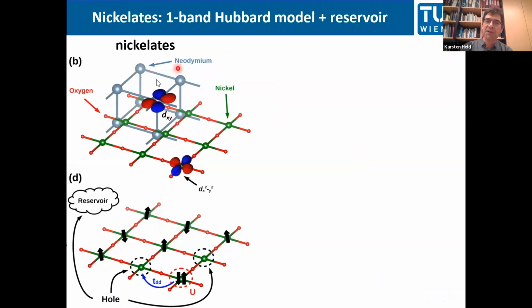It's important, this electron pocket, to get the right hole doping. So if you make a chemical hole doping, part of the holes go to the pocket, the reservoir, and part go to the Hubbard model. But I've done many DFT plus DMFT calculations before, and that's actually the first time I dare to describe a real material with a Hubbard model, if we have this translation.